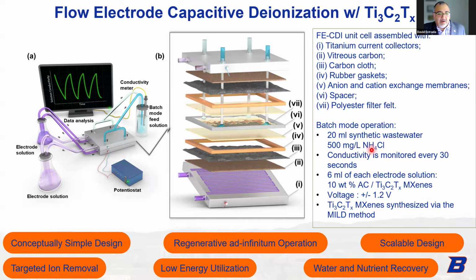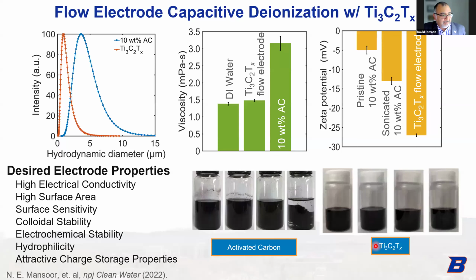We're using ammonium chloride to simulate the ammonia that might be present in these agricultural waste streams. So this just shows the stability of our electrodes. In this case, we're still working with the Ti3C2 MXenes, and we're comparing to activated carbon.